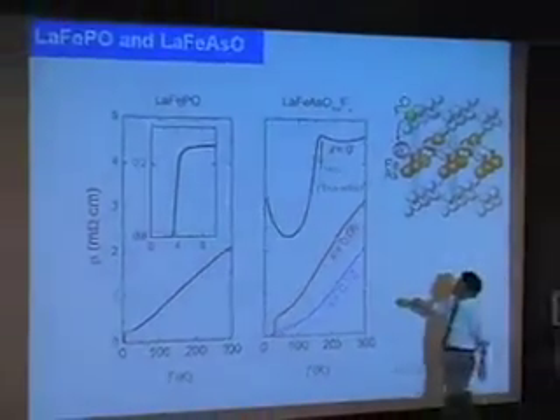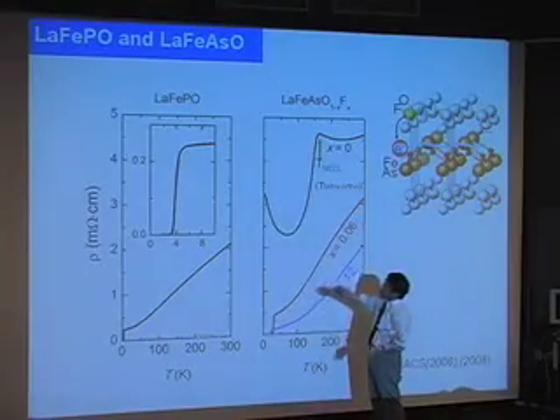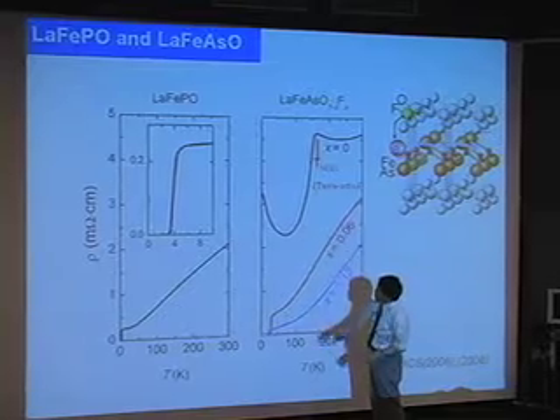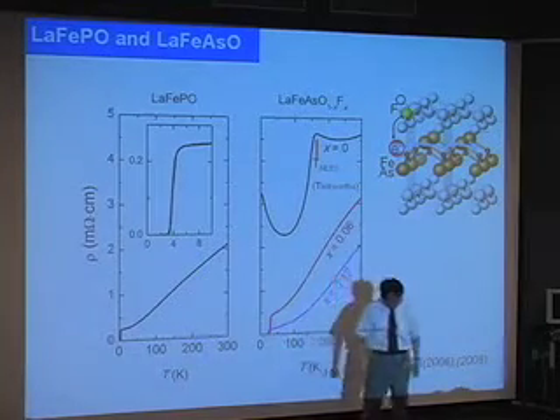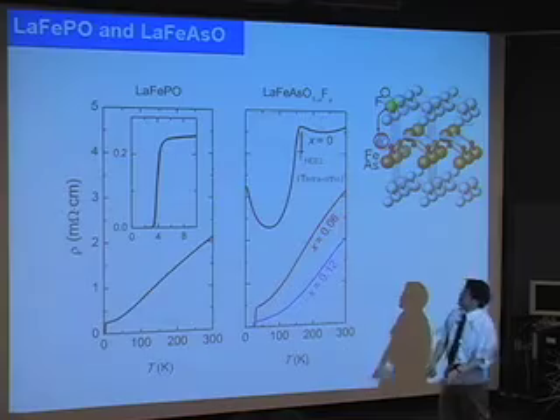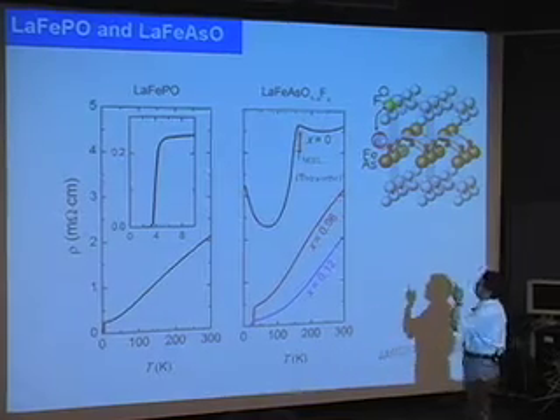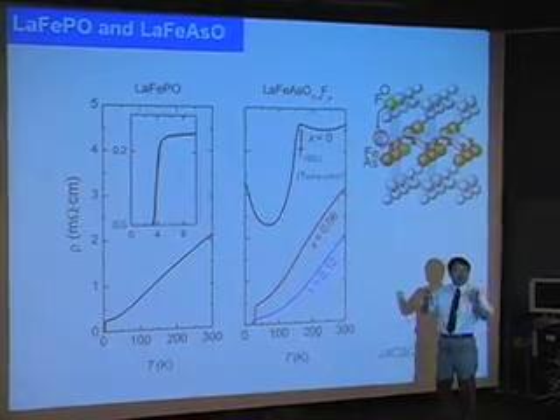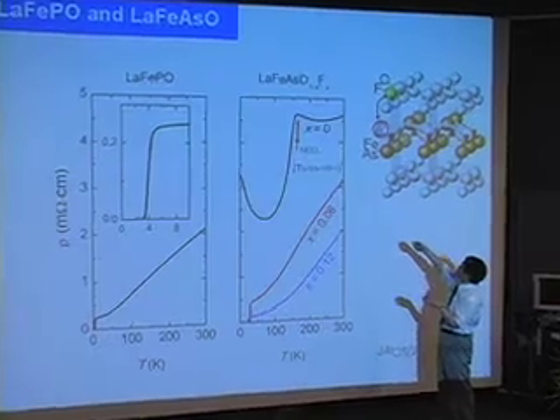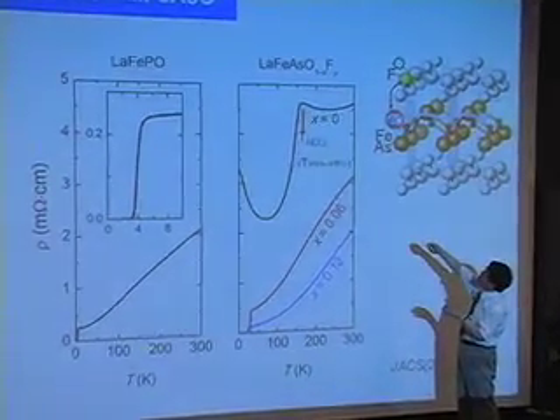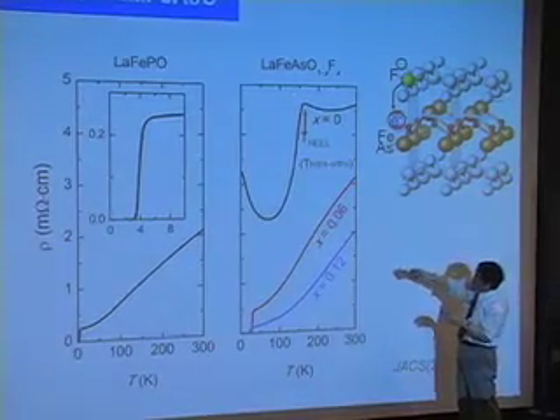The phosphorus state is without doping. When the sample cools down, superconductivity is observed. So we replaced the phosphorus ion with arsenic, and in the arsenic case, when the temperature goes down, it behaves like this.